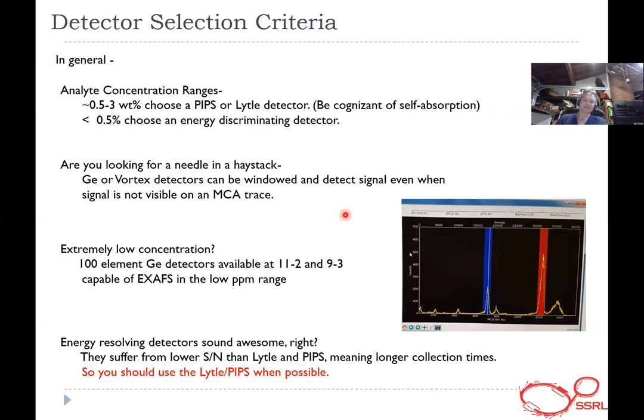But they suffer from lower signal-to-noise than Lytle and PIPS, which means longer collection times. Also, in higher count rate situations, if you're using a monolith, you can get crosstalk, where you get shared charge between channels, which creates a broadening of your energy resolution. So if you don't have to use them, don't. You should get away with a PIPS or a Lytle detector, or transmission, if that's the kind of concentration regime you're in.